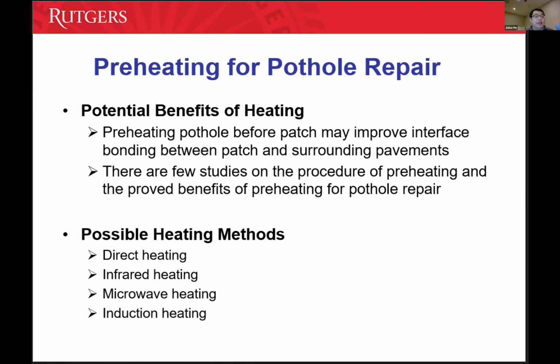We also looked at microwave heating. We did some trial study. It can also heat the material pretty quickly, but the mechanism is different. In microwave heating, you are heating the material from inside, by molecular excitation, so you are not just heating from the surface, which is what infrared heating does. If you are doing deep pothole or deep-depth heating, microwave will bring some benefits. But for shallow heating, it's not as effective as infrared. That's why we selected infrared as the first trial for this project.